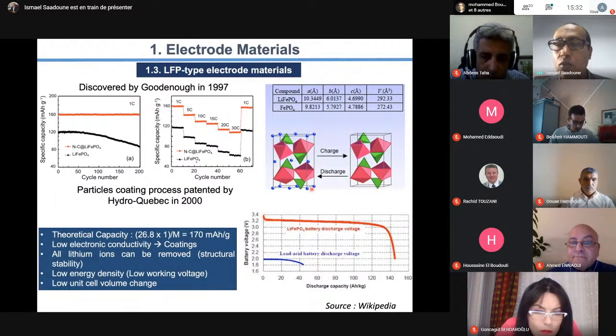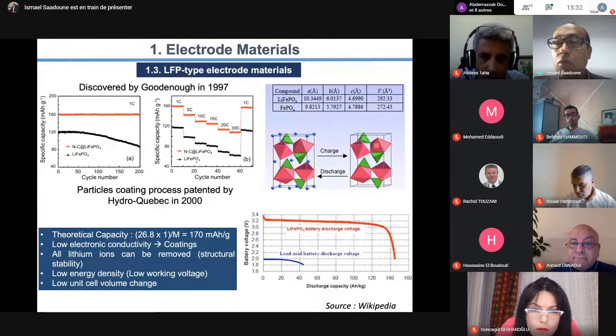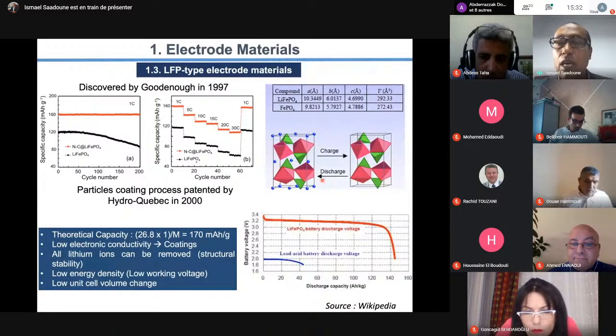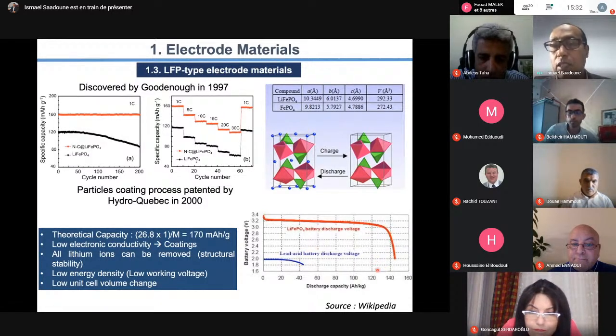We have a plateau - equilibrium between LFP with lithium in blue and without lithium. So here we have this material, and here this one. You see we will compare the capacity of LFP with what we use now in our cars - we have 4 times the capacity, 4 times the autonomy. But the problem of phosphate is its low conductivity.